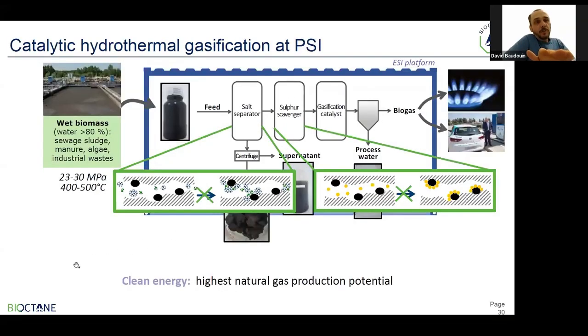Next slide, please. The advantage, from a process point of view, and that is why these two steps before the catalyst step were developed and optimized, is to prevent the catalyst from being exposed to salt deposition, so from clogging. The salt separator is here to remove salts and solids that could deposit on the catalyst bed. And the next step, the sulfur scavenging, is a very important one, as biomass can contain a lot of sulfur and a very broad variety of sulfur compounds. So the sulfur scavenger is a key aspect in the process. Next slide, please.